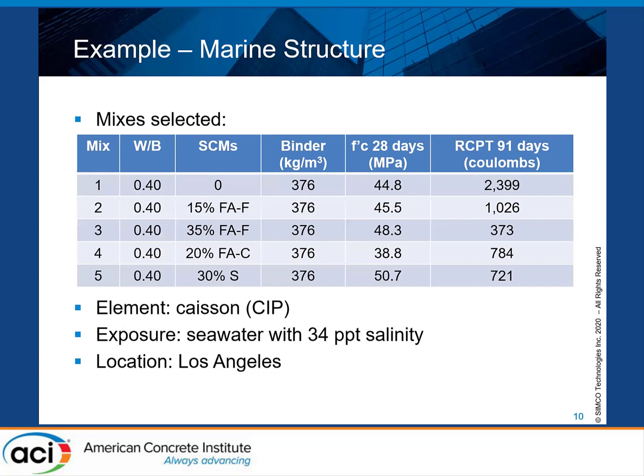I picked 5 mixes in our database that would all be compliant with the requirements of these 2 codes. They all have a water binder ratio of 0.4, but different types of SCMs and different replacement levels of those SCMs, and they have all the same binder content. So I know you may think the binder content is low, but this was for a research project, and the binder content was kept constant for all mixes.